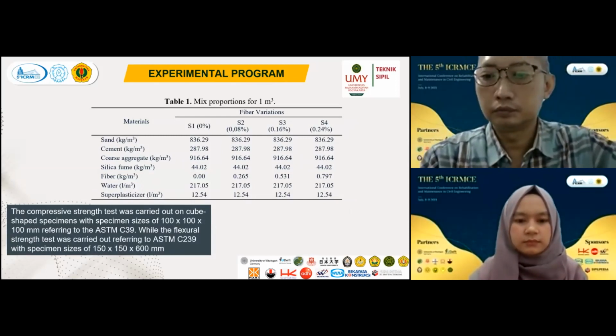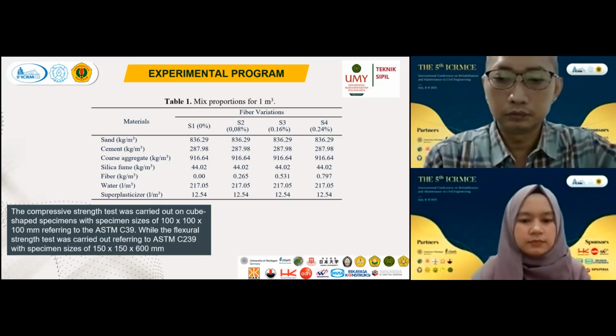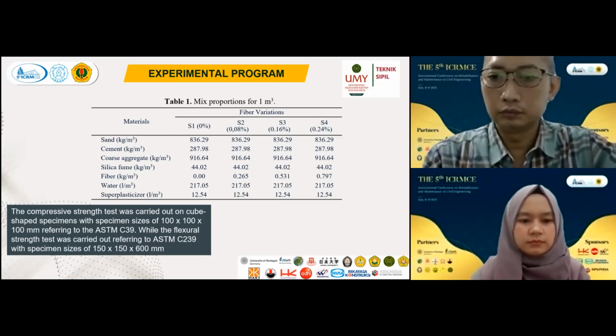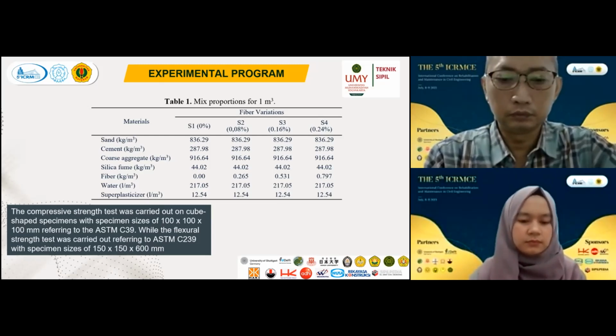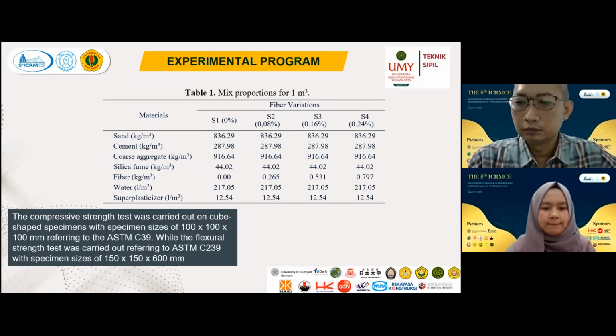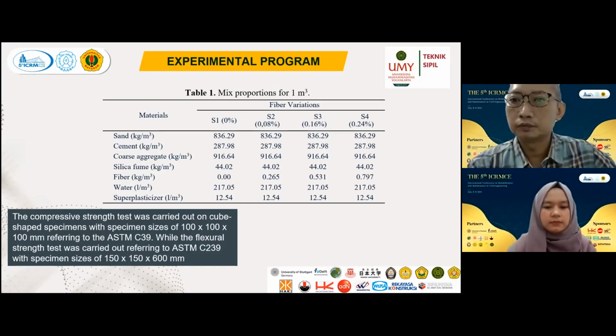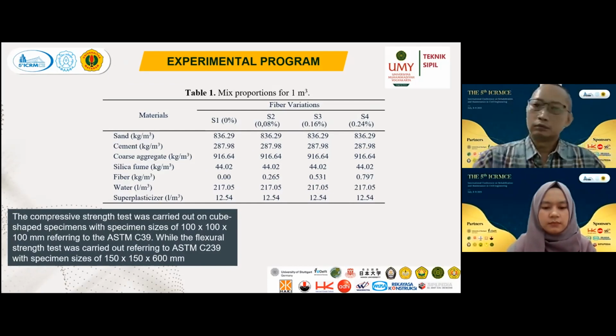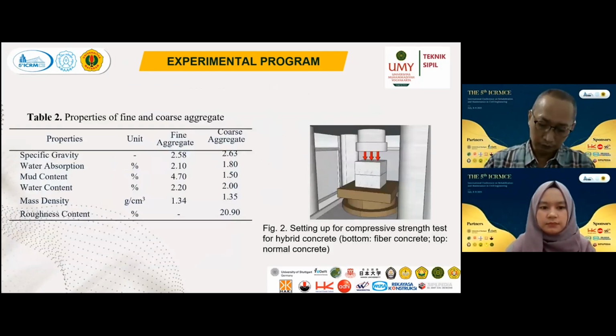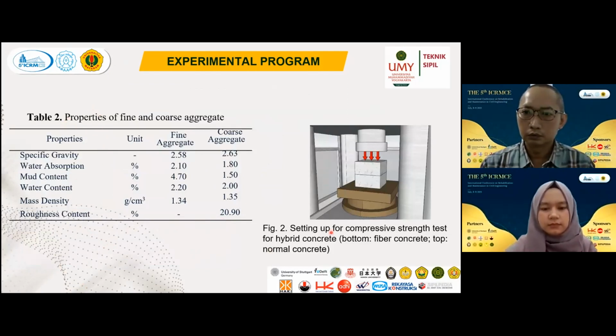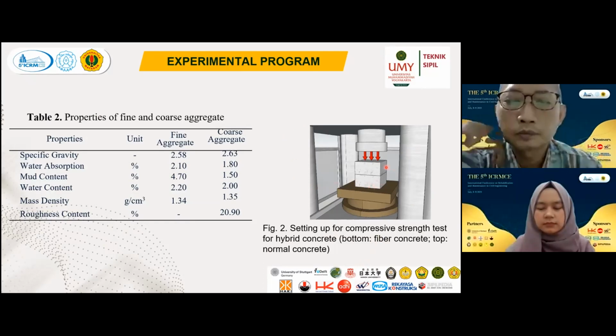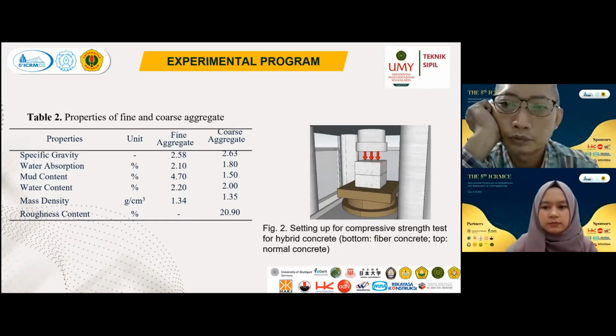The compressive strength test was carried out on cube-shaped specimens with a size of 100 by 100 by 100 mm, referring to the ASTM C39, while the flexural strength test was carried out referring to ASTM C239, with specimen size of 150 by 150 by 600 mm. This is the properties of fine and coarse aggregate, and this is a figure of the setup for the compressive strength test for hybrid concrete. On the bottom is fiber concrete, and on the top is normal concrete.